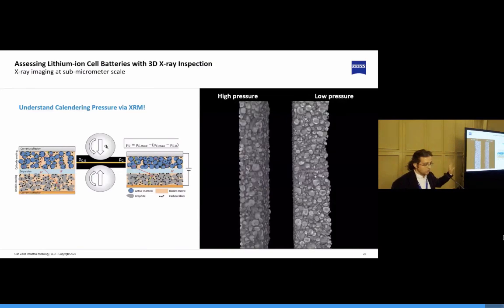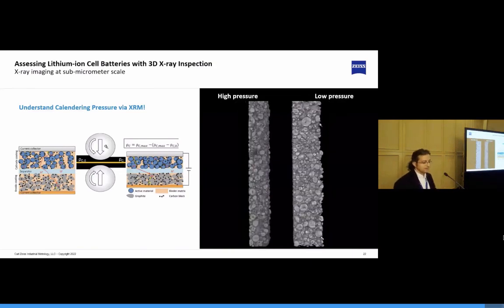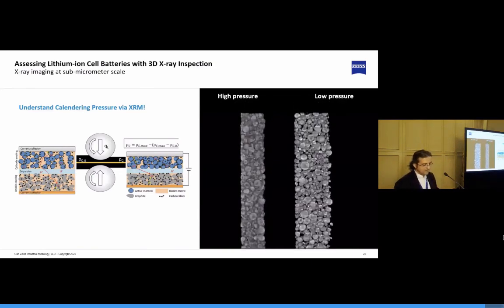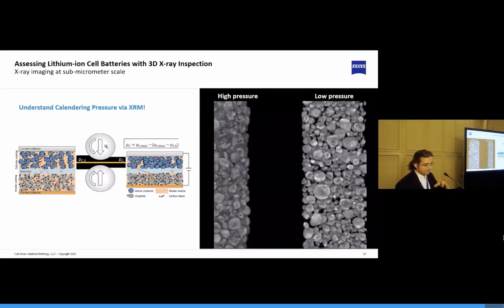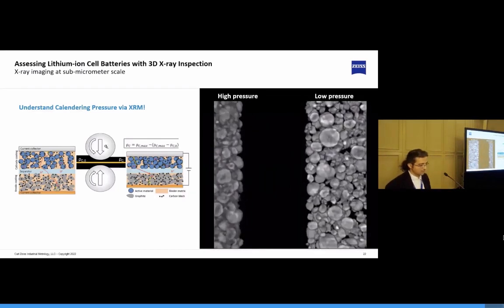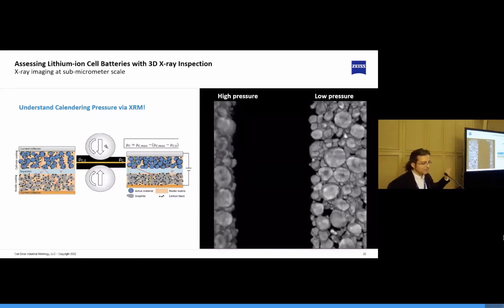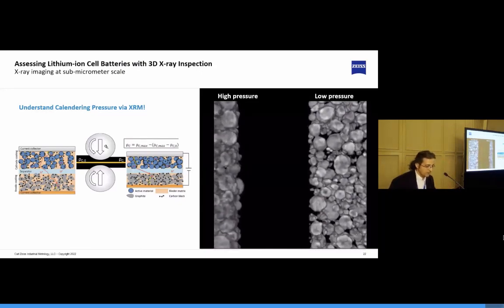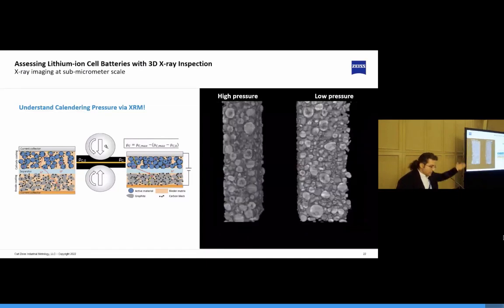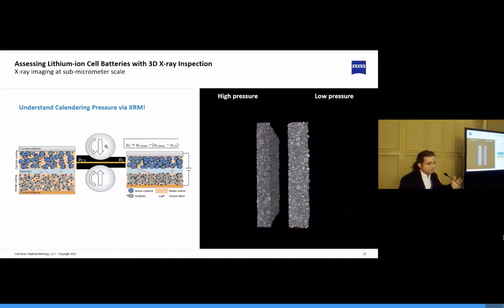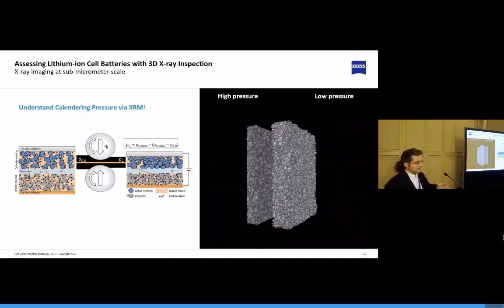The two cathodes shown in the video have been compressed at different calendering pressures, resulting in differences of density of the particle packing and porosity of the electrode. So potentially affecting the electrochemical performance of the battery cells. You can clearly see the low pressure calenderings lead to cathode particles that are separated too far apart and with voids in the binder material. This will be reflected in suboptimal energy density or poor charge capacity of the battery.